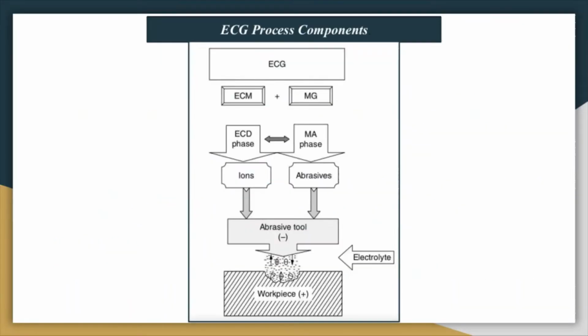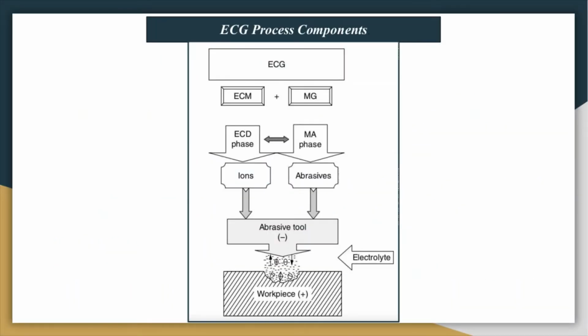Now, the performance of the electrochemical grinding process results from the interaction between mechanical abrasion and electrochemical dissolution and changes in the surface layer properties of the material in the machining area. Increasing the longitudinal feed rate and wheel speed and decreasing the voltage result in a smaller gap width and consequently an increase in the mechanical abrasive contribution to the EMRR process. By decreasing the feed rate, the cutting process is considerably reduced, down to values near zero at the transition to pure electrochemical dissolution.